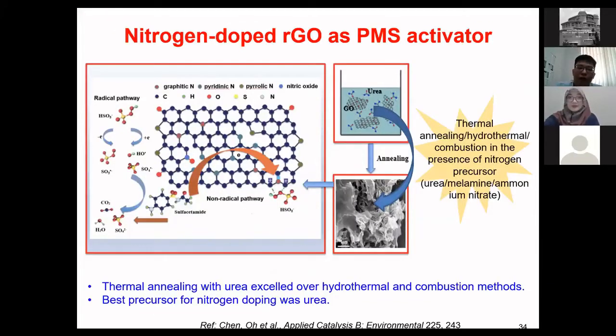So for some innovation to improve the performance, we looked into doping. Right? We dope this nitrogen functional group on the carbon catalyst. For this study, we look into reduced graphene oxide. So we prepare this reduced graphene oxide and then we dope some nitrogen, which means we introduce certain nitrogen functional groups on the surface of that particular catalyst, and then we test it out for removing antibiotics. Okay? And we carry out certain optimization process. We look into thermal annealing method. We use hydrothermal method and combustion method to see which way is the best way to prepare this kind of catalyst. And we found that thermal annealing is the best, and using urea is the simplest and most economical approach.